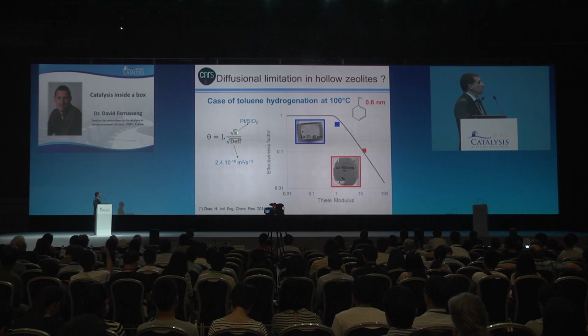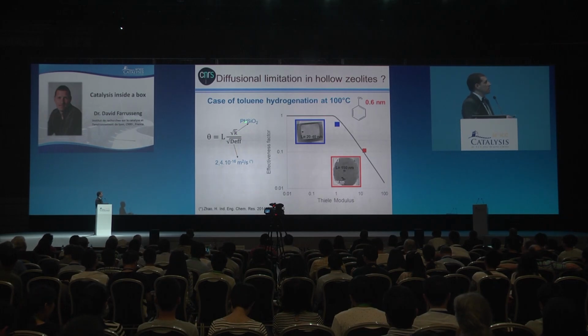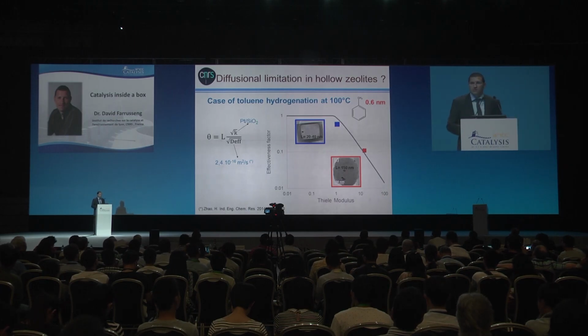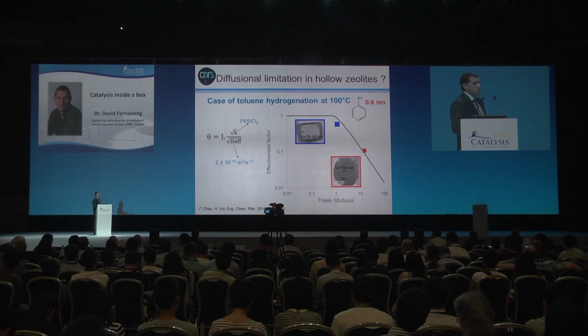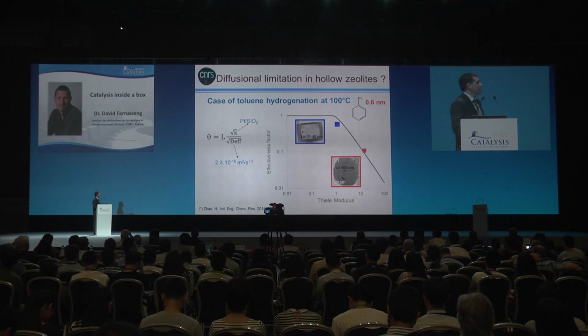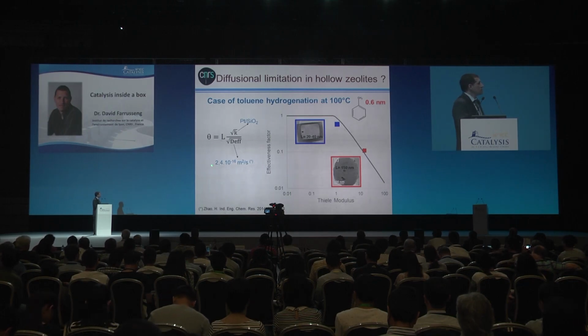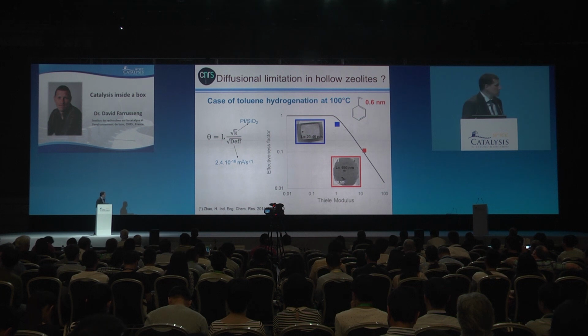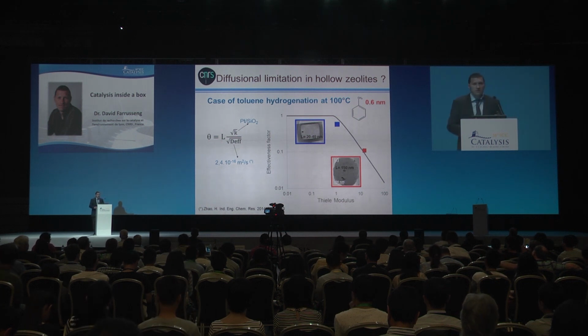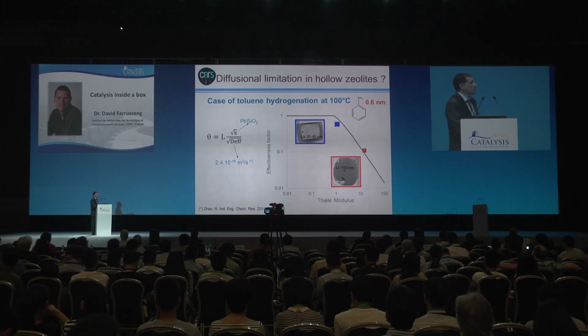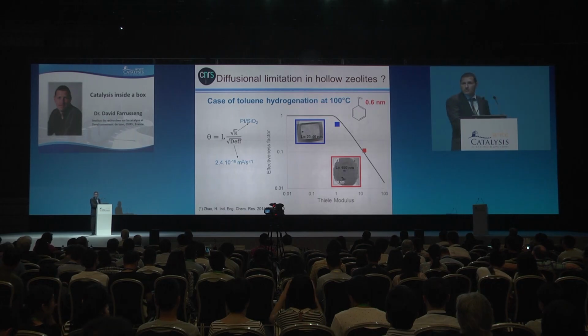So for the rates, we have measured the platinum on silica. We could have also taken numbers from the literature. So this is outside, of course, diffusional limitation. This is intrinsic to the platinum catalysis. And for the denominator, we have taken a value from the literature, which is the diffusion rate of toluene in silicalite-1. So this term, you can do nothing about. It's imposed by the system.